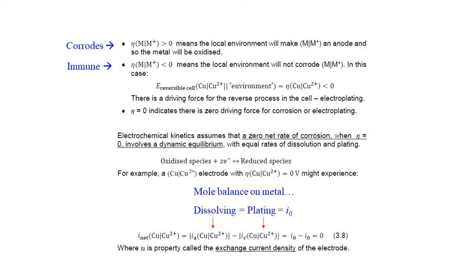Second conclusion, if the polarization of the metal electrode is negative, then the local environment will not corrode the metal to metal plus electrode. In fact, in that case, the reversible cell potential with the metal, say the copper metal at the anode, is negative, and there's actually a driving force for the reverse process, which would be, for example, electroplating of the copper. Third conclusion, if the polarization of an electrode process like copper to copper 2+ is zero, that means there is zero net driving force for either corrosion or electroplating. In that case, thermodynamically, we predict no corrosion happening going forwards.